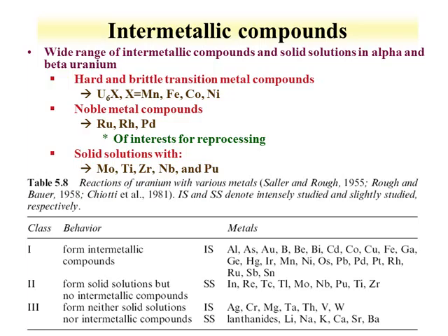Similar to the solid solutions, the metals can also form different compounds. The alloys, as we've already talked about, are just where the metals form fundamentally solid solutions, where the metal ions are just replacing each other. Intermetallic compounds can also form, and these are compounds that have specific stoichiometries. So, for instance, uranium with manganese, iron, cobalt, nickel, that composition in stainless steel, can form a U6X compound.